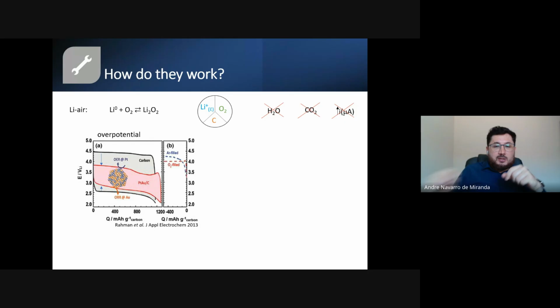So this is 2013, one of the first results in lithium oxygen batteries, about 10 years ago. So this is how this battery works. The potential is about 3 volts in these batteries. When we discharge the battery, we have a kind of plateau here. That's the plateau when we are forming the lithium peroxide. Then when the cathode is full of lithium peroxide, we stop the discharge process and then we recharge the battery.